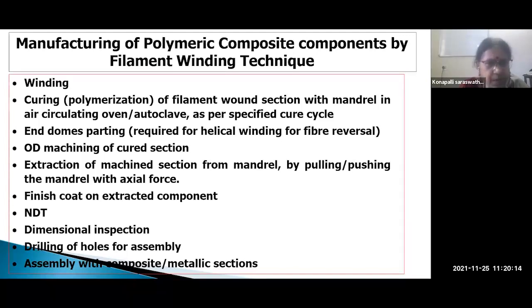So generally, composite will be designed by degrading 10% of mechanical properties to cater for machining operation, because near net shape only we can make. Then once we machine it, we extract the machined component from the mandrel by either pulling or pushing the mandrel with axial force. Then only can the component be extracted from the mandrel. Then of course, finish coat as per requirement, as per aesthetic we can give.